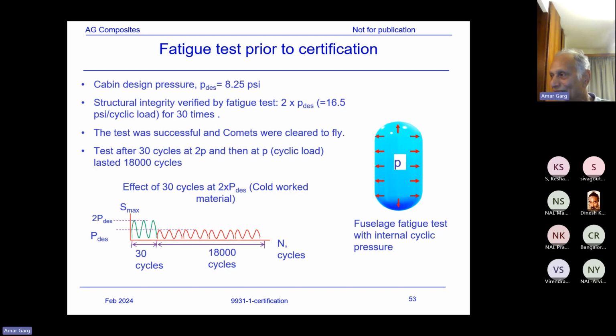Now, this is a practical thing which happened in a real structure, the overloading effect. And such a tremendous retardation effect of overloading in aluminum. So when you are doing the fatigue design of aluminum structures, compared to composites, which don't normally show that retardation effect or load cycle effects, metals are very crucial. One cannot ignore the overloading, retardation or sequencing effect when doing fatigue design. So that is why testing of metallic components becomes more difficult in fatigue than composites, which I'll be talking about later on.